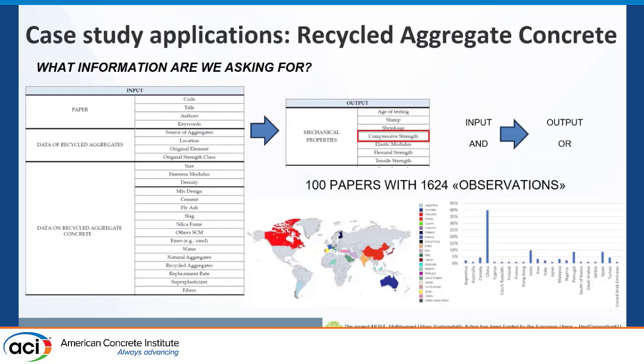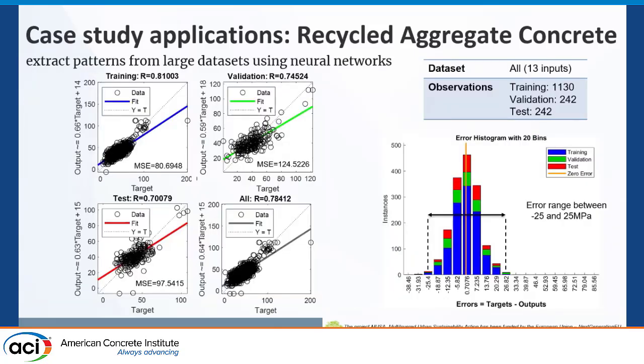1,600 data points. Many of them came from China, but there was also a good geographical distribution. And we looked into compressive strength, the easiest thing that everybody will do. We trained our neural network, but we ended up with a very large error: 25 megapascal plus or minus, totally unacceptable.